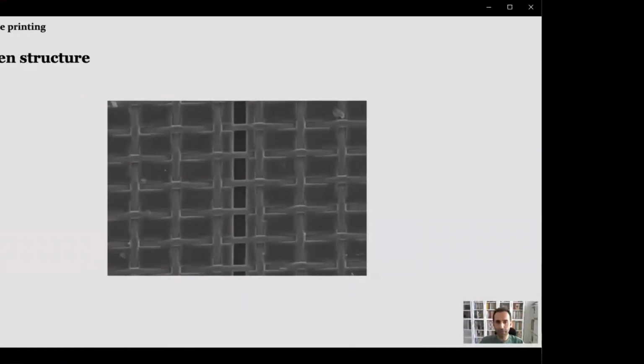Mesh wires are perpendicular to the opening and the knots from the wire stay underneath the emulsion. The advantage of this design is obvious: grid line resistance can be lowered and narrower grid lines can be printed. However, it still has some disadvantages, such as low throughput, since knotless screens cannot handle the shear pressure by the squeegee like a regular screen. The whole process needs to be slowed down. That's why these screens are not mainstream yet.